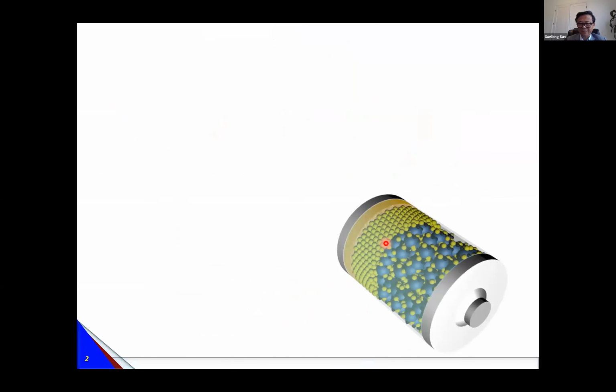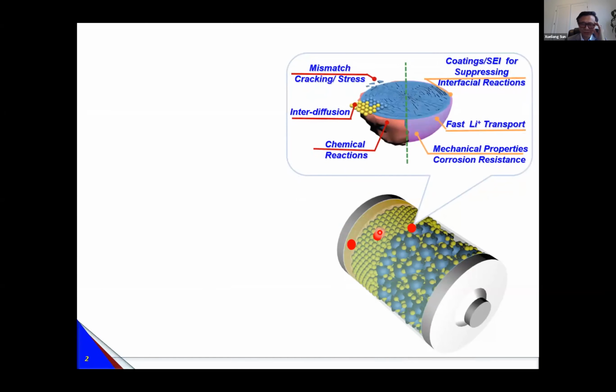So for example, here we talk about this solid-state battery structure, where the challenge is basically, for example, the interface. You already talked about the interface. And also Shirley and Donghai will talk about the interface too. For example, the interface with the anode, lithium metal, and also the interface with the cathode. And also here is the solid-state electrolyte. For example, the interface with the cathode has a lot of challenges. For example, mismatch, cracks, stress, interdiffusion, and also electrochemical reactions. So people are using different strategies to address it. For example, using coating, using coatings/SEI to suppress the interface reactions.